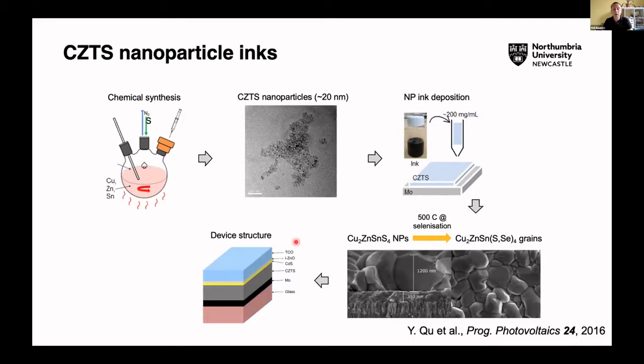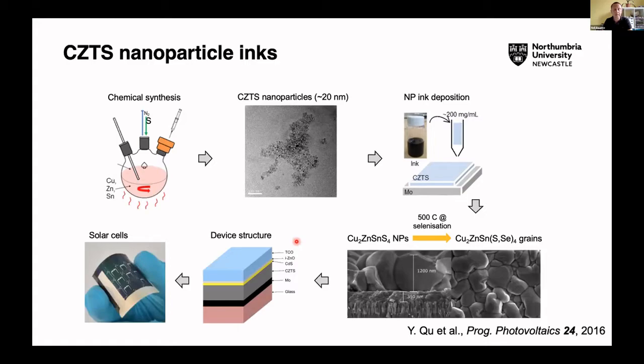We have a conventional thin film architecture and a substrate configuration, and we deposit our CdS on top of our photovoltaic absorber and finish in the usual way with zinc oxide TCO before putting contacts down, and then we can make solar cells like this on different substrates. This one is a molybdenum foil substrate. So that's our basic fabrication process, if you like.